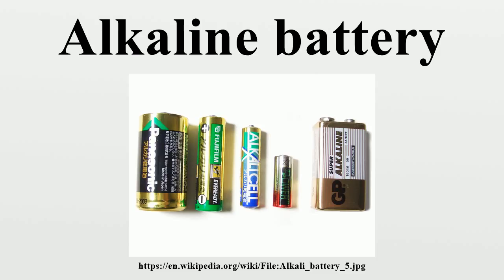Capacity of an alkaline battery is greater than an equal-size Leclanche cell or zinc chloride cell because the manganese oxide is purer and denser, and space taken up by internal components such as electrodes is less. An alkaline cell can provide between 3 and 5 times the capacity. The capacity of an alkaline battery is strongly dependent on the load. An AA-sized alkaline battery might have an effective capacity of 3000 mAh at low drain, but at a load of 1 ampere, which is common for digital cameras, the capacity could be as little as 700 mAh.